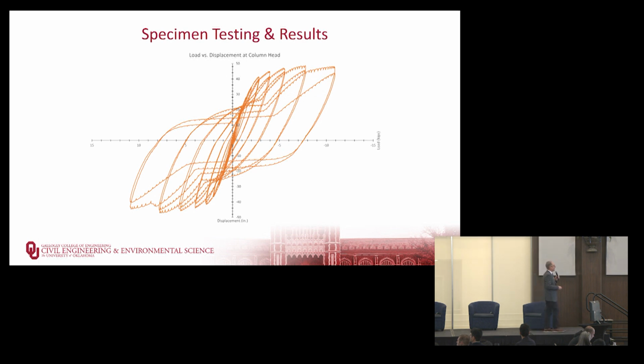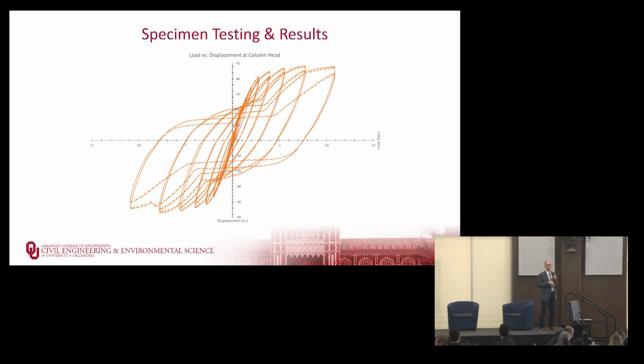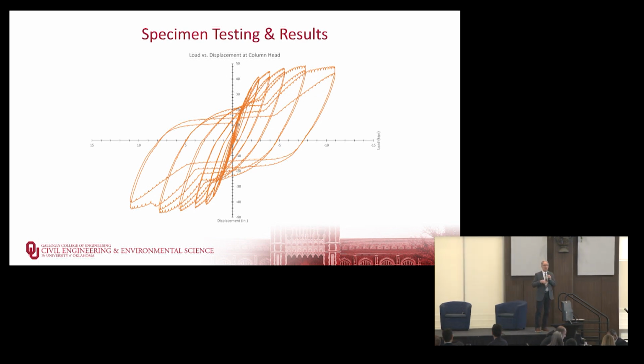And then this is the exact same column, same steel, same FRP, but with the ultra high performance concrete on the inside. And you can see, we get that same linear elastic response. We start to yield the steel tube. Concrete starts to become nonlinear.